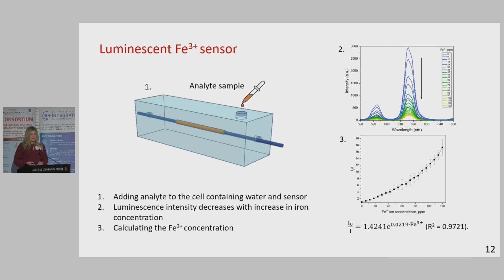So if we wanted to use the sensor that we're developing, first we would have to have this sensor suspended in water cell to keep the polymer hydrated and to allow the ions to penetrate the polymer structure and interact with our MOF sensor. Then we would measure the light intensity emitted by the sensor without any iron present, and then measure again the intensity of the light with the iron present. And if we measure the ratio between these 2 intensities, we can determine exactly how much iron we had in our sample to begin with.